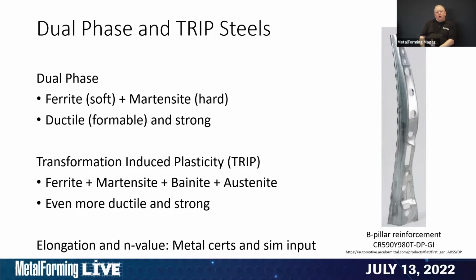And along with that comes very high n value for both dual phase and TRIP steels. And where that is really useful is that those properties do wind up on metal certs. We get them from a simple tensile test. So they're on the metal certs and they're key inputs into forming simulation software. Over the years, simulation packages have developed and advanced where, when we're talking about drawn parts, they predict formability exceedingly well. So for dual phase and TRIP steels, that isn't a problem.